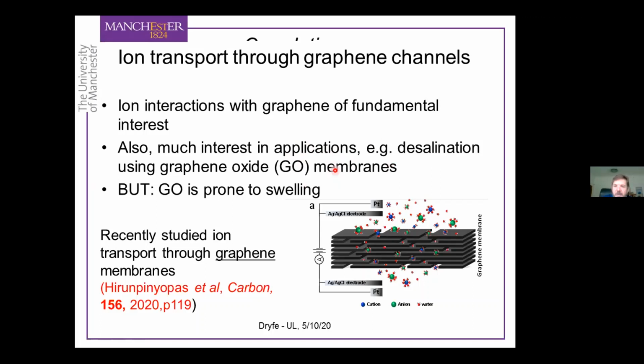And the interesting thing about these membranes is that the capillaries that form between the restacked graphene oxide are about a nanometer or a little bit less in diameter. So in principle, they're about the same as the size of hydrated ions. So a lot of people got excited about 5 years ago with the idea that you could use graphene oxide as a desalination membrane. Basically, graphene oxide is hydrophilic, so water would pass through it easily, but it would sieve out ions, and therefore you could turn salt water into fresh water. There's only one problem. Graphene oxide is so hydrophilic that it swells. So the problem is that graphene oxide can be used for desalination as long as you don't get it wet.